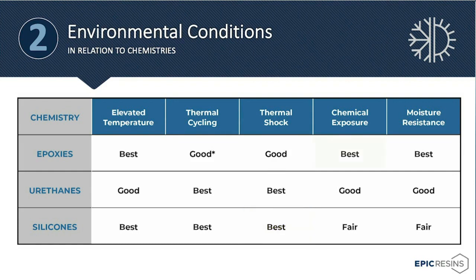When you're talking about chemical exposure, epoxies would have the best chemical exposure. When you're talking about chemical exposure, it really comes down to cross-link density. Epoxies have the ability to have high cross-link density, which allows them to resist chemical attack. Urethanes, because they can have high cross-link density, have the ability to have good chemical exposure properties. As you have high cross-link density in urethanes, again, that reduces chemical attack. Silicones, on the other hand, are fair. Because they have lower cross-link density, they don't have quite as good chemical exposure properties as epoxies and urethanes.